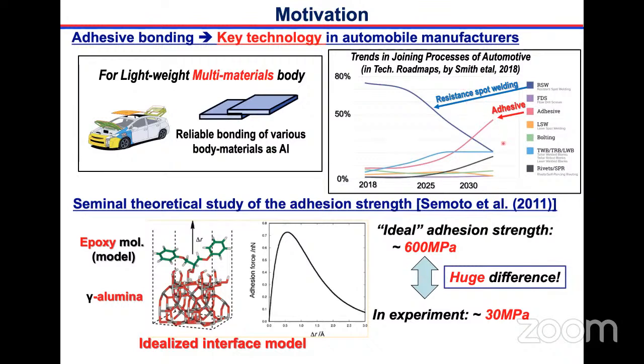So there is a strong motivation that we can perform the theoretical analysis of the adhesive bonding method. Of course, there exists a seminal theoretical study of the adhesive strength. This was done by the Japanese group here. They prepared gamma alumina, because gamma alumina mimics the surface aluminum oxide. Then they put the epoxy molecule model here, and they got the curve, the force-displacement curve, something like this.